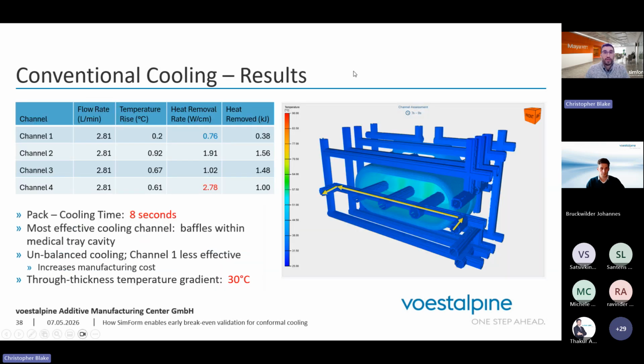So here are the results for the conventional cooling design. We can see that indeed our pack cooling time was confirmed to be about 8 seconds. We also determined that the most effective cooling channel is the one that has baffles going into the working surface or the cavity of the medical tray where you actually store things in the tray. But we also noticed that there is unbalanced cooling in the sense that channel 4 on the underside, which is the one we're seeing on the screen, is extracting the most heat. And channel 1, which is in the stripper plate, is the least effective.